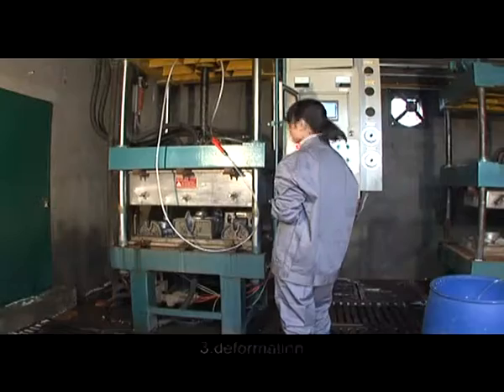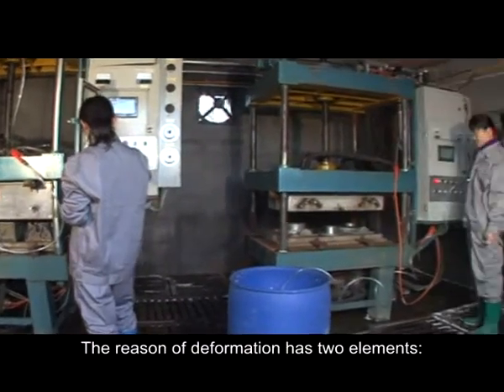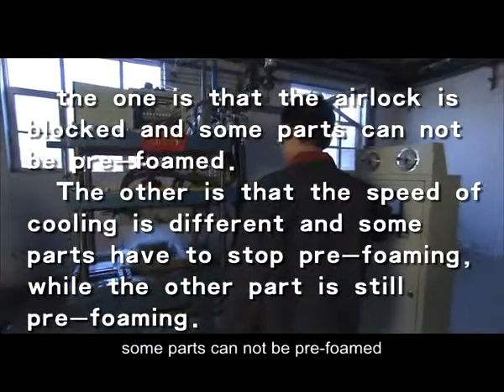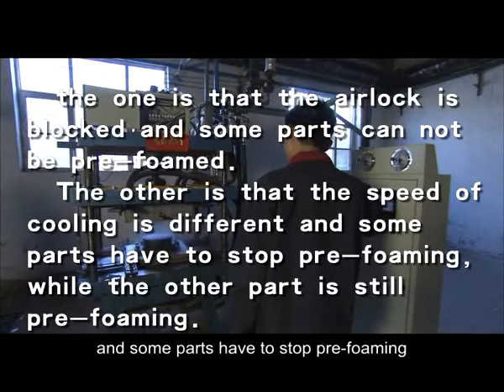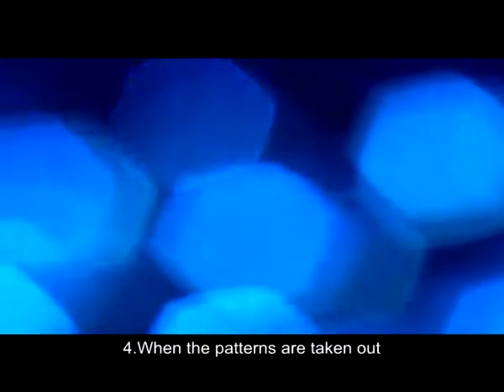3. Deformation. The reason for deformation has two elements. The one is that the airlock is blocked and some parts cannot be pre-foamed. The other is that the speed of cooling is different and some parts have to stop pre-foaming, while the other part is still pre-foaming.